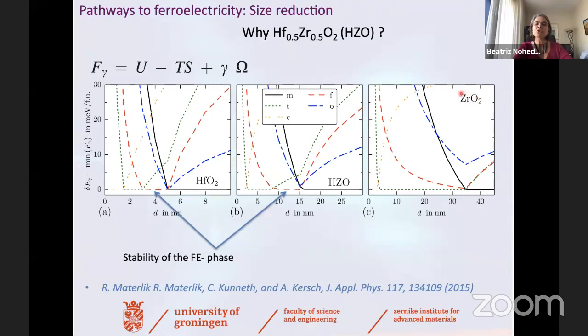Now, interestingly, if you go to pure zirconia, as I said, zirconia and hafnia have the same valence, they have the same ionic radius, but of course they are different. And the main difference between them is actually in the surface energy. So you can see that in zirconia, the ferroelectric phase is never the ground state. So one cannot get pure zirconia ferroelectric, but you can mix the two of them, and you can see that by mixing zirconia and hafnia 50-50, you can increase the stability of the ferroelectric phase to larger radius. And this is very important, of course, for applications, that you can go to a little bit higher thicknesses.